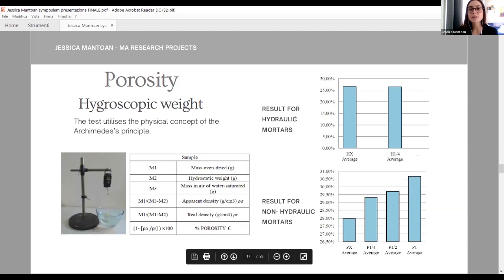In the case of the hydraulic mortar, we can see that even if the distribution of porosity is quite changed in relation to the use of barium hydroxide, the final percentage of porosity of the two mortars is exactly the same, and that is a quite positive result. On the opposite, the results related to non-hydraulic mortar showed that the percentage of porosity increased directly with the amount of barium hydroxide used for the preparation of the mortar. As I said in the beginning, usually when mortars are used as a sacrificial material, presenting a higher level of porosity can be considered as something good.